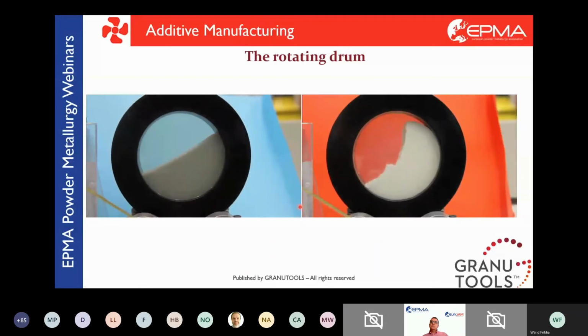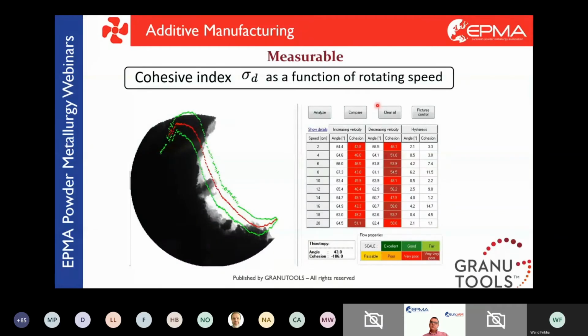What we are doing with this rotating drum principle is measuring the temporal fluctuation - the amount of fluctuation in the powder bed versus time. We take a picture of the blue video every second for 30 seconds, so we have 30 pictures and compare those 30 pictures to each other. Then we do the same with the red video and see the deviation of the average angle. I'll give you the final result directly.